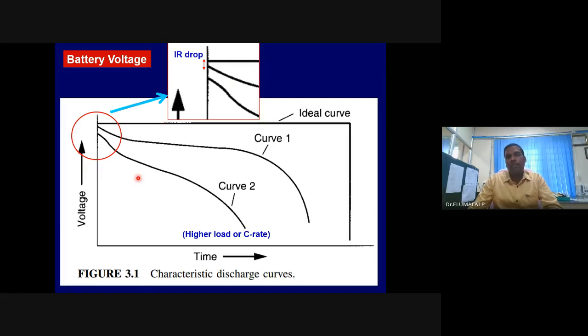Since there are 3 curves, you can call them 3 discharge curves. A discharge curve is nothing but a plot of voltage versus time. A plot of cell voltage versus the time during discharge. In any ideal condition, any ideal battery should have this kind of plateau potential. Once all the charges are consumed, then the battery should decline to 0, should reach the 0 potential.